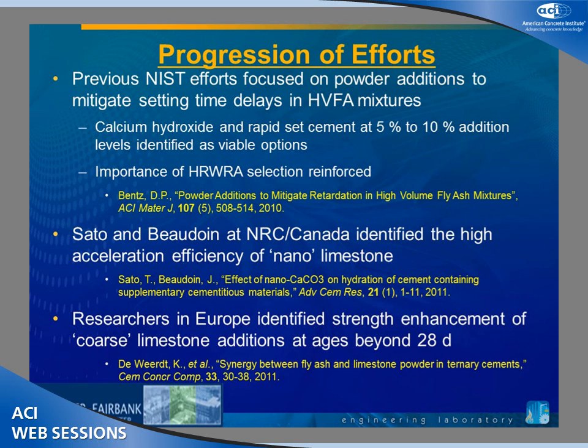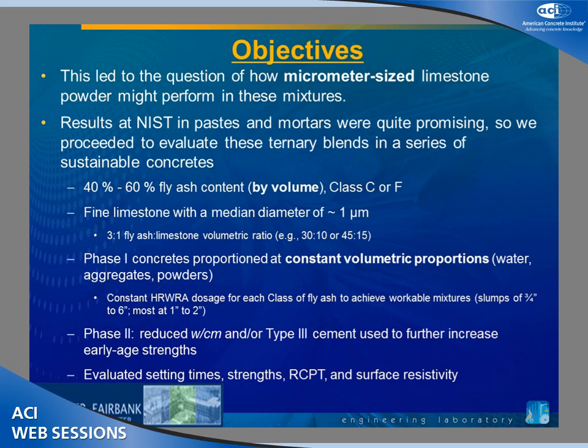And while the calcium hydroxide and rapid set cement worked quite well, the limestone that we were using, about 15 microns average particle size, had almost no influence on changing the setting times. So this got us to thinking, and we thought, well, we know nano limestone is doing a lot, the coarse limestone is helping at later ages. What about this whole range that goes between nano and 15 microns?